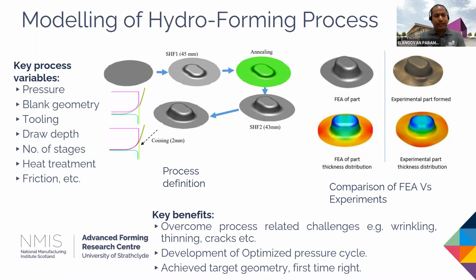And in terms of defining the depth, that is also an important parameter. Like if you want to achieve a certain level of thickness in the final formed part, the definition of such depth in each process step is quite important. And then depending upon the complexity of the part geometry, we need to define the number of process steps. And sometimes it may require heat treatment as well. So these are the typical process parameters we consider by doing a series of experiments.